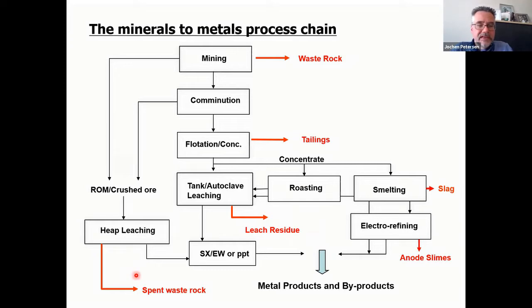In heap leaching, we have the spent waste rock. Once the ore that's been piled on a heap has been leached, it no longer contains leachable material and can either be left behind or disposed of in a separate waste disposal. And smelting, as I said earlier, separates a metal from a non-valuable phase, referred to as slag, and that is disposed of as a metallurgical waste. And finally, in the electrorefining of copper, you also have a waste referred to as anode slimes, which are of particular interest because they are one waste stream that has historically already been recovered, because it contains a lot of valuable metals as a byproduct of the value chain.